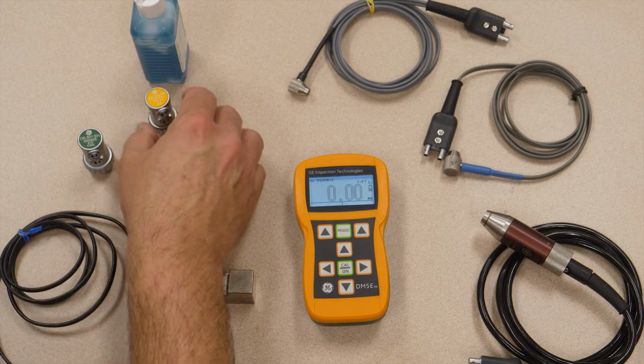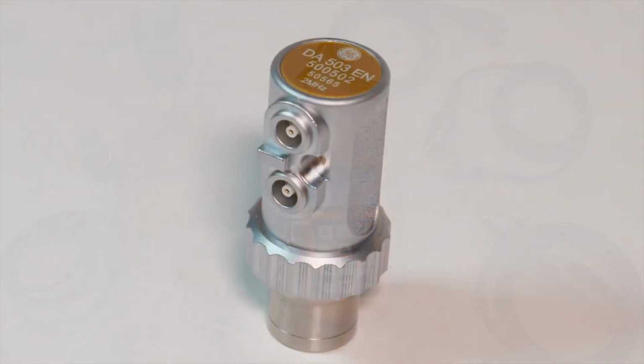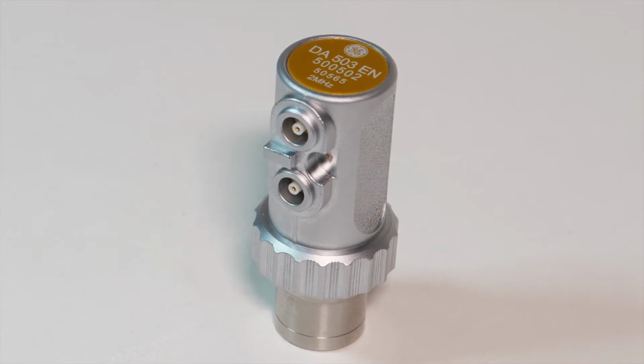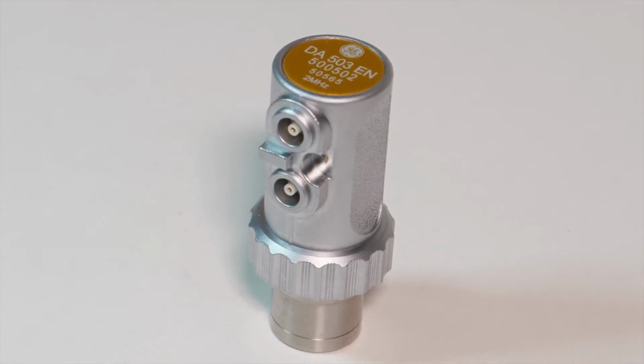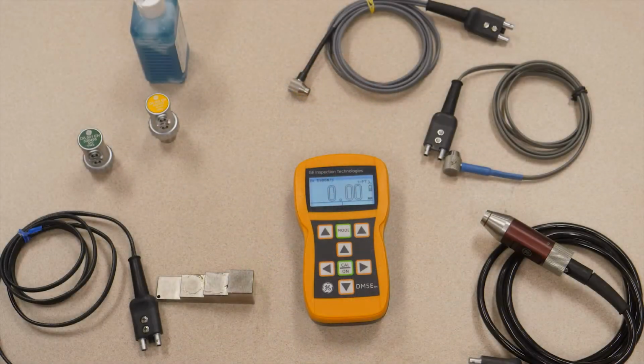The DA503 is a lower frequency, larger diameter probe. It is ideally suited to coarse-grained materials, highly attenuative materials, thicker materials. With the DA503, you have a measurement range of 5 millimeters to 300 millimeters, or about 200 thousandths to 12 inches. All right, so thicker materials, DA503.